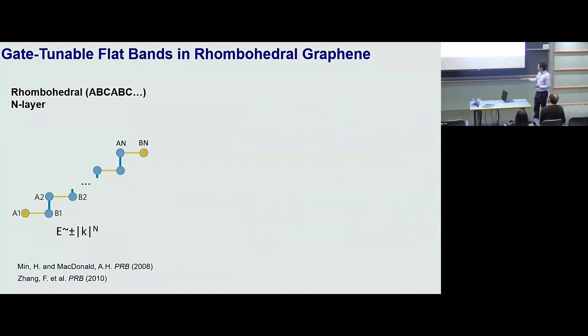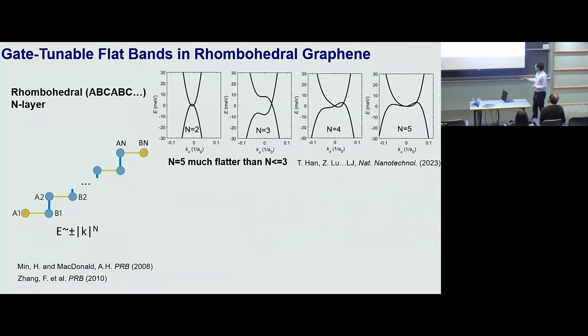And this tells you that if you have monolayer graphene, you get the famous linear Dirac band, very big Fermi velocity, nothing to do with a flat band at all. But if you crank up the layer number to 2 layers, 3 layers, 4 layers, 5 layers, very quickly you can notice that in the neighborhood of zero energy, this band becomes more and more flat. When you get to something like 5 layers, although this is not a parabolic band at all, if you put a parabolic band there and compare the density of states in the range of, say, 5 meV, you can actually tell the band here is already so flat, it's comparable to an effective electron mass of something like the bare electron mass, okay?